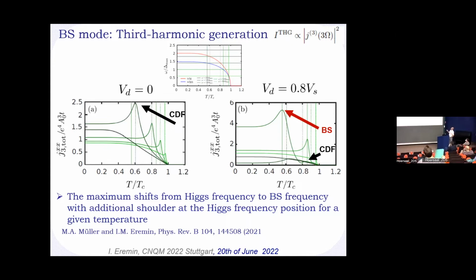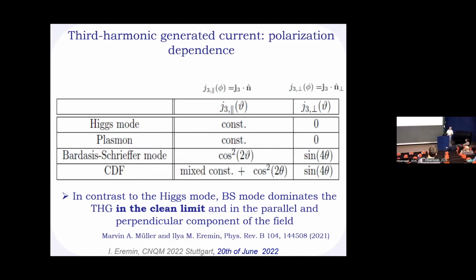Important is that once you introduce a non-zero interaction in the D-wave channel, you suddenly see that the response becomes dominant in the Bardasis-Schrieffer mode. And you only develop a kind of shoulder, the charge density fluctuation, and the position of this Bardasis-Schrieffer mode is actually much higher than that of the charge density fluctuation, which tells you that in a clean limit, if you're probing an unconventional superconductor and you see a response which is of the order of 2 delta, you better check that this response is not coming from what you believe is a Higgs fluctuation, but actually something which is more a signature of the subdominant mode.